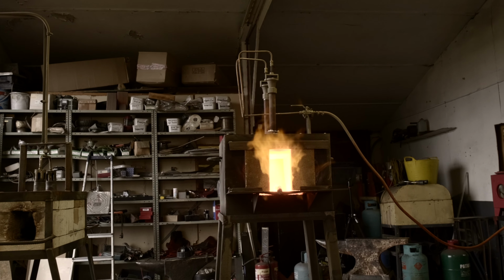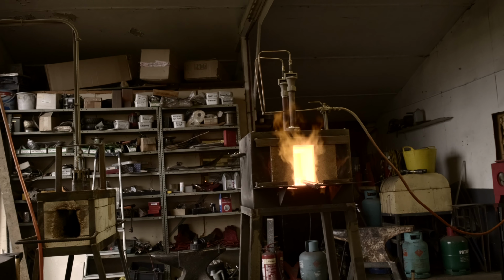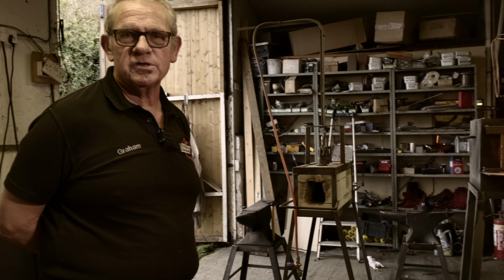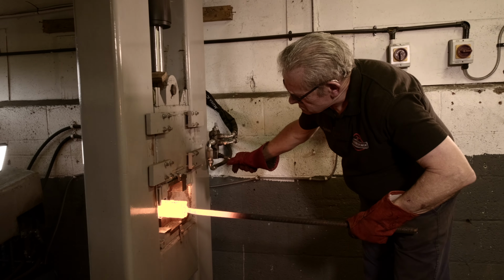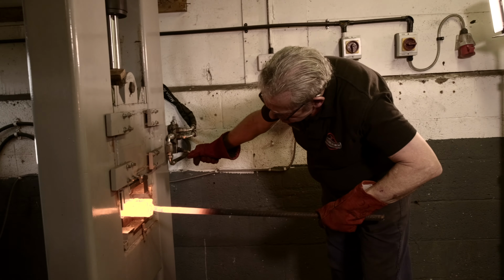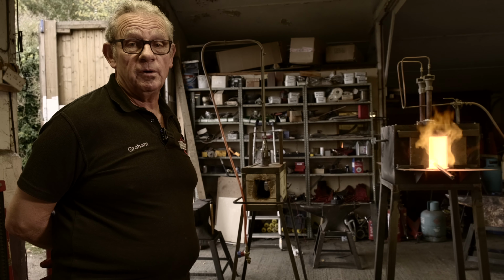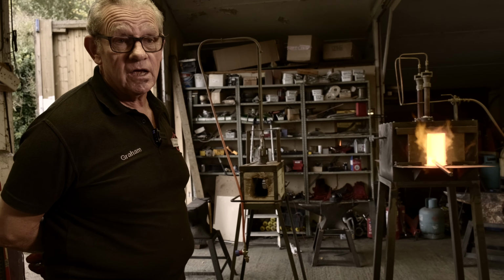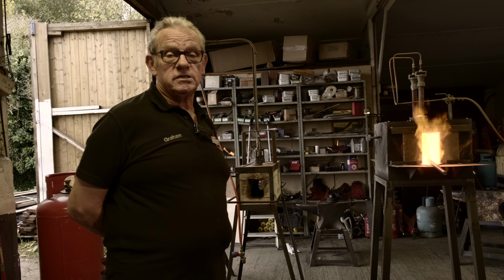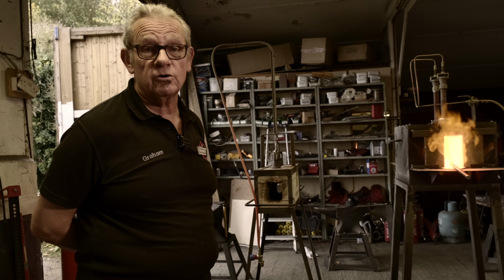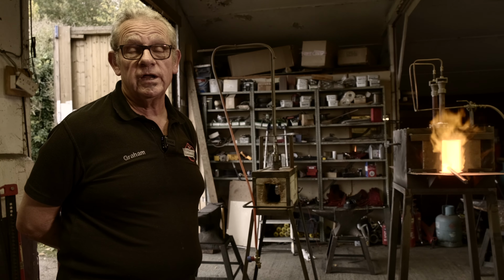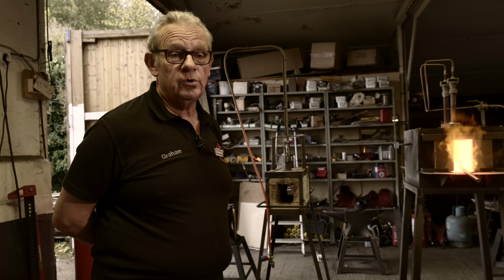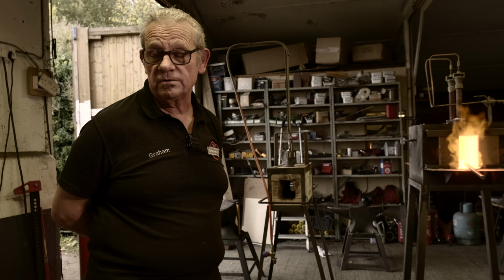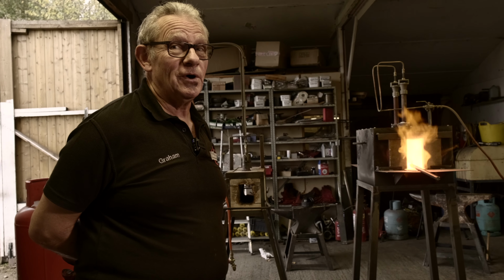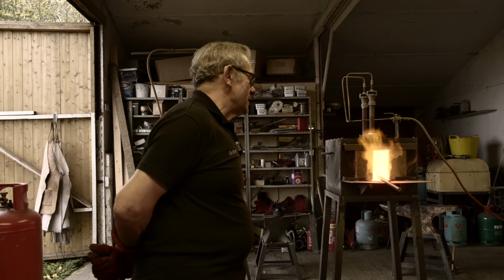Now, during the early stages of forging down, while that block is still big and heavy, it takes quite a long time to come back up to temperature. But when we get it into the press, because it's a big block, it doesn't lose the heat quite so quickly, so we get a bit more forging time. As the billet gets longer and thinner, it heats up quicker, but it also cools down quicker when it goes into the forge. So we don't get quite so much time to do the forging. Everything in metallurgy is a compromise, always making allowances for something.